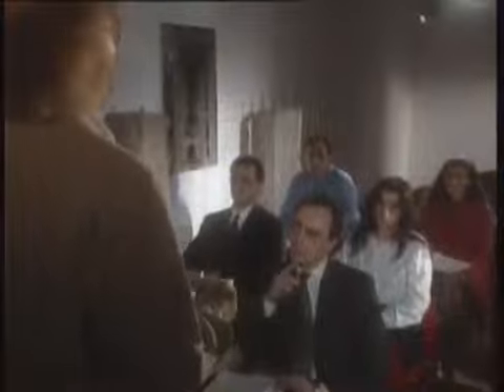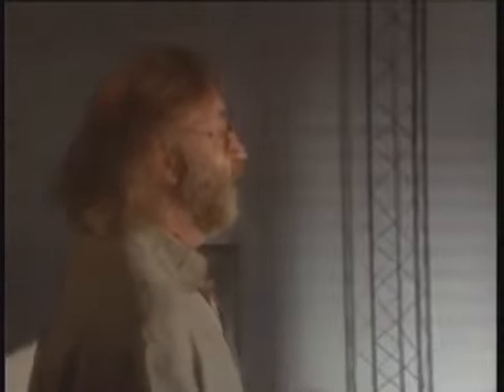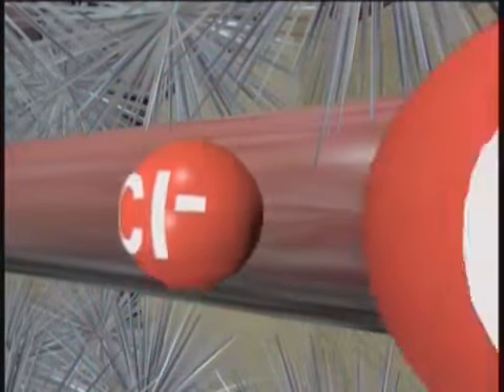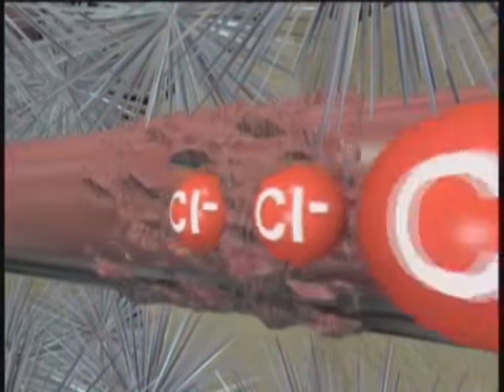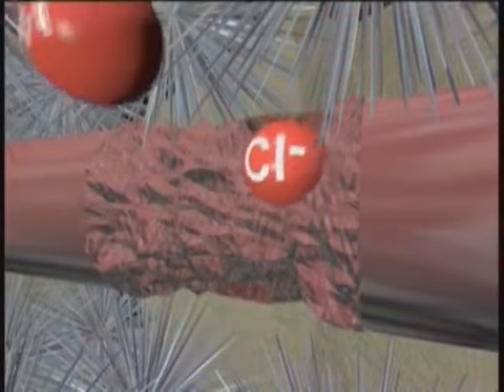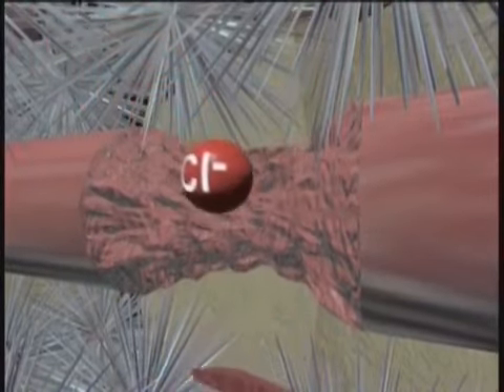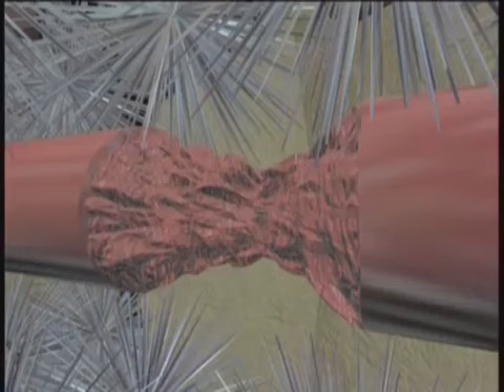The thin rust layer, which encloses and protects the steel bars, remains stable and compact as long as the amount of chloride remains below 0.2–0.3% by weight of cement. If, however, the percentage of chlorides increases, the rust layer becomes porous and no longer guarantees any protection to the steel reinforcing bars. The metal undergoes localized pitting corrosion, which dangerously reduces its diameter.